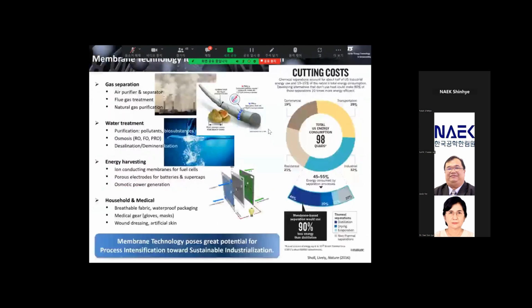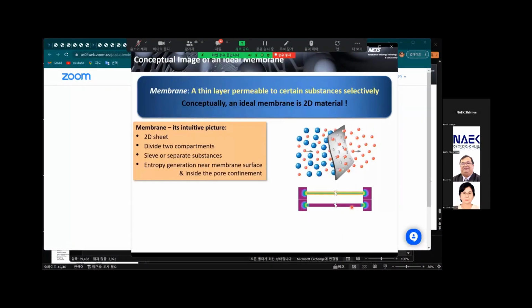But we can do something about the transport-related dissipation. This dissipation is primarily caused by a friction mechanism. In theory, we may decouple the friction-related dissipation from the separation-related dissipation and get rid of the latter to obtain energy efficiency in chemical separation. Or we could also thin down the membrane to decrease the portion of the friction-related energy dissipation. And at the limit of this strategy, we come to the thinnest feasible membrane that nature allows, an atomically thin membrane.